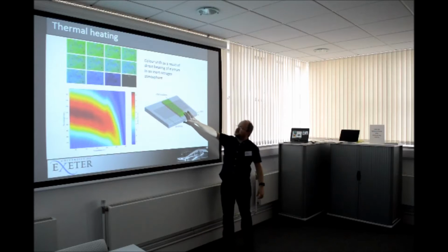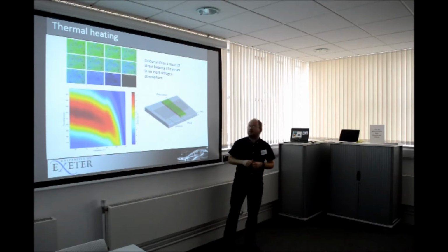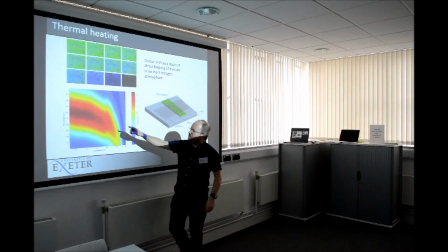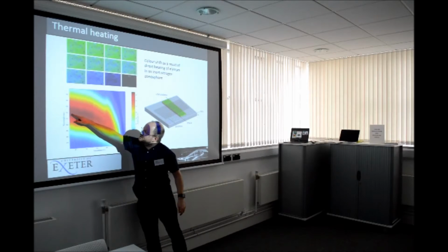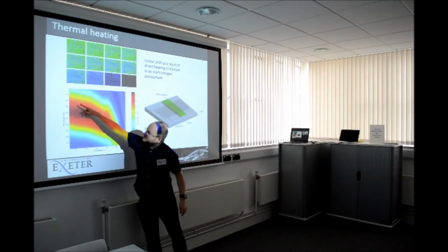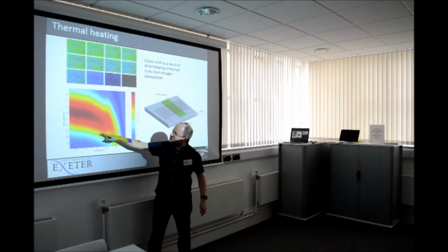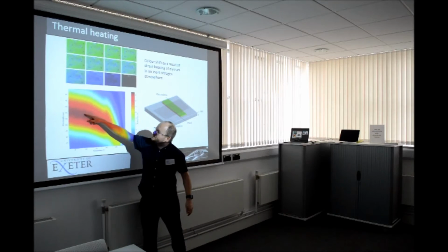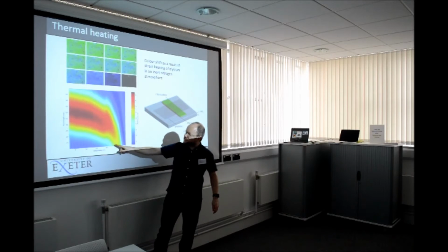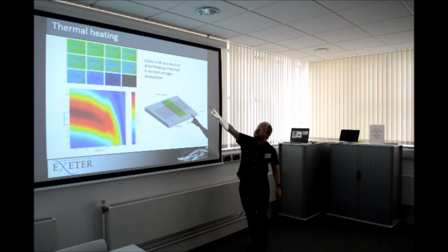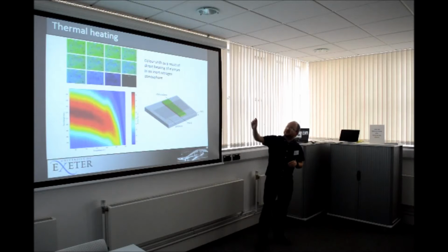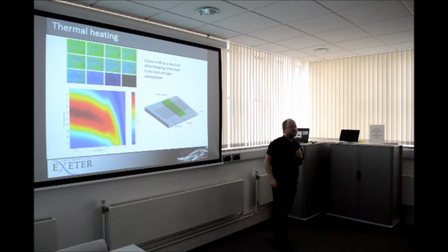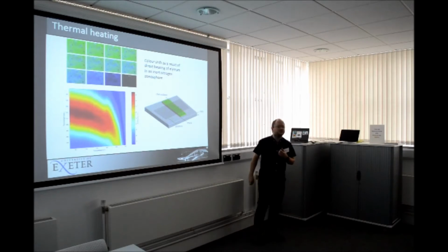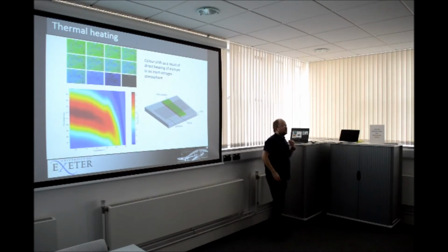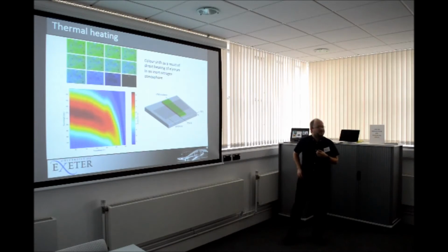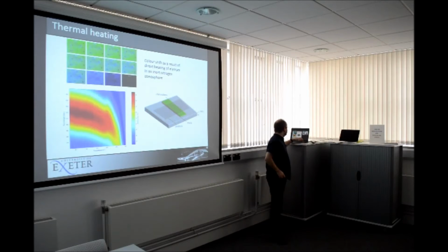They heat it up two ways. One, they heat it up just by increasing the temperature with a hot plate. And what you can see here, although I won't explain it in much detail, is the wavelength they're observing, this axis, as a function of temperature. This is their maximum peak colour changed as the temperature increased, and you can see it up the top there in those little images.